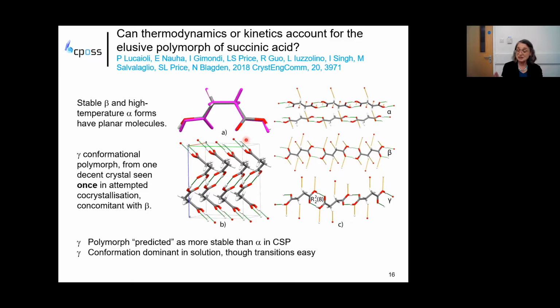And he tried, but he could not reproduce this crystal. But as far as the theory was concerned, yep, we could predict it. It was more stable than the alpha polymorph in the crystal structure prediction. And also, simulations agreed with the experiment that actually in solution, the molecule should be bent rather than planar, as it was in the most stable form, though the molecular dynamics did show that the transitions are easy.